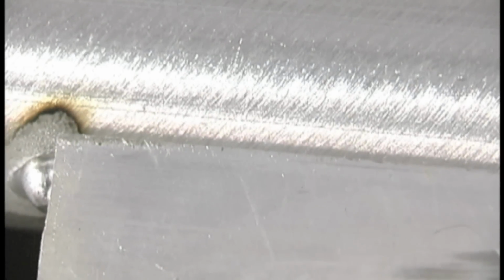So waiting and waiting and waiting, and eventually that thick piece will get enough heat to puddle, and eventually I can join the two, and then heat will conduct once I get the two joined, and then I can proceed with somewhat of a bead here, but not much of one. Not really welding that clean, not really welding that good, not hot enough, not near hot enough, but can join them. That's maxed out at 180 amps, and then we'll do the same thing with the Everlast.